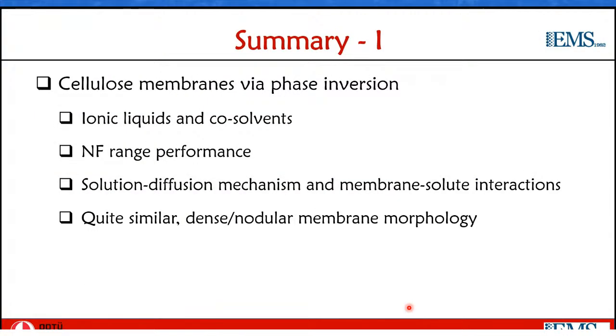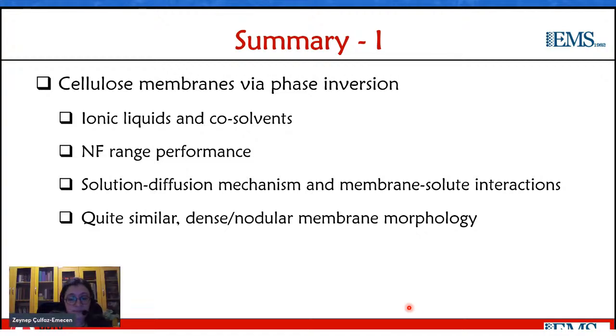So summarizing the first part, I've shown you cellulose membranes fabricated by phase inversion using an ionic liquid and co-solvents in the polymer solution with nanofiltration range performance. The transport through these membranes seems to be occurring through solution diffusion, and membrane-solute interactions there are quite dominant. And although we can tune the membrane performance by changing the fabrication parameters, morphology-wise, all the membranes were quite similar looking: all symmetric, dense, and nodular structures.